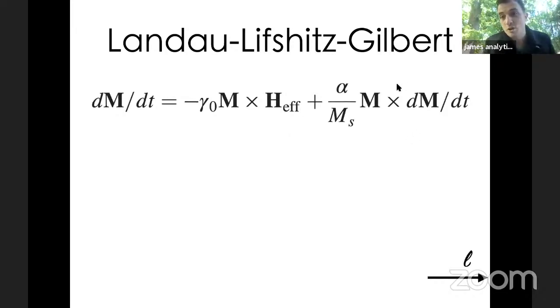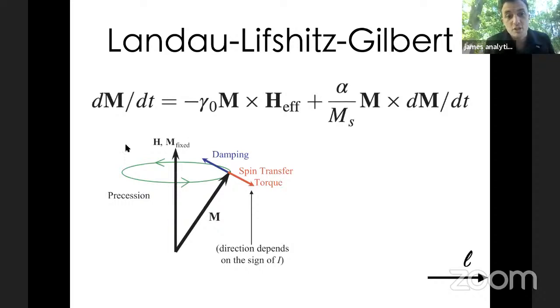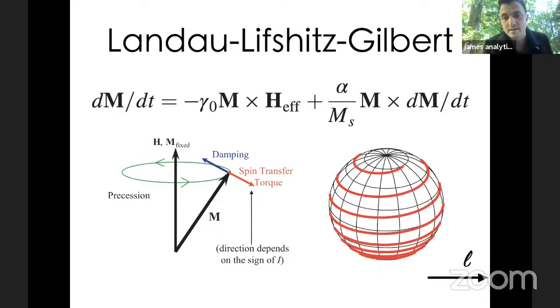And then a second term, which actually creates precessions of the spins around an axis. And actually that anti-damping term can also rotate your Néel vector, sometimes even in the same direction as this field-like term. Okay, but it's in general a relatively complicated process, but I think mostly it's understood, certainly in the case of ferromagnets.